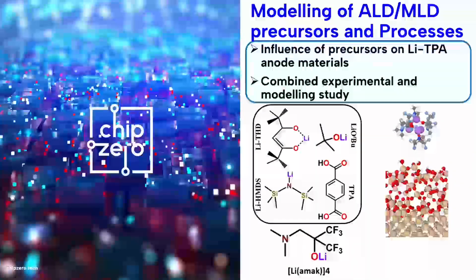And we are also working on looking at the effects of different precursors on the deposited material. So for instance, we have preliminary experiments on these lithium precursors where we see that one of these, which is the lower one, results in a slightly different material than the other ones. So the question of why this is, we're simulating this with this methodology to then try to learn what it is about these precursors that leads to a different type of material.